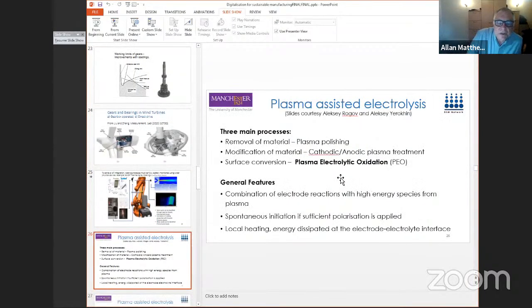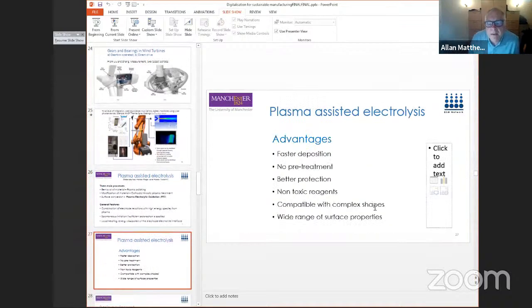We've done this type of approach in a technique called plasma-assisted electrolysis, which can be used as an in-liquid plasma, which can be used for plasma polishing, for treatments, and for coatings. And that particular technique is extremely useful as an alternative to anodizing. So compared to anodizing, it has no toxic reagents. It doesn't use, for example, sulfuric acid, which conventional anodizing does use. So this particular technique is ripe for utilization in a sustainable manufacturing scenario.